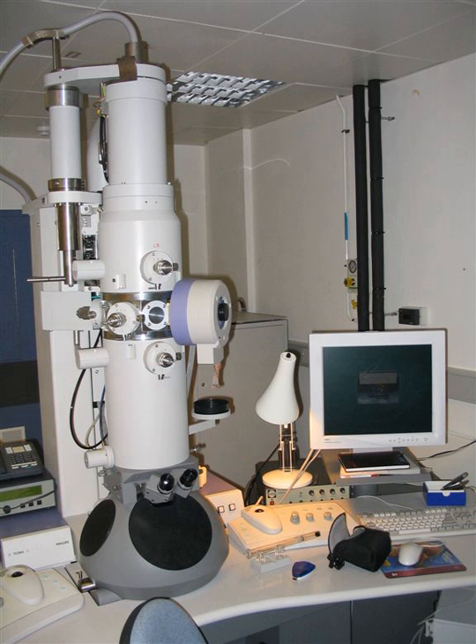Replication. A surface shadowed with metal, e.g. platinum, or a mixture of carbon and platinum at an angle is coated with pure carbon evaporated from carbon electrodes at right angles to the surface. This is followed by removal of the specimen material, e.g. in an acid bath, using enzymes or by mechanical separation to produce a surface replica that records the surface ultrastructure and can be examined using transmission electron microscopy.